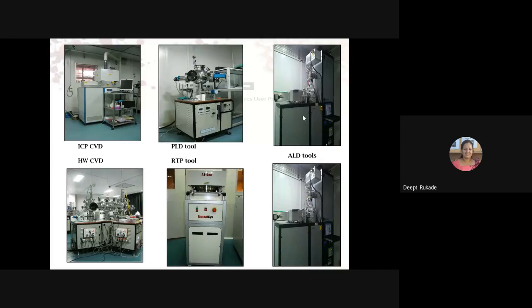I need to grow a very thin oxide, for some tantalum oxide. I need a very thin layer of around a few nanometers, say 5 to 12 nanometers. So RTP is the best tool. You send in oxygen gas, and once RTP is done for that silicon wafer, what you get as a result is some oxide which is as thin as 5 to 12 nanometers. So I have put it as a growth tool also.